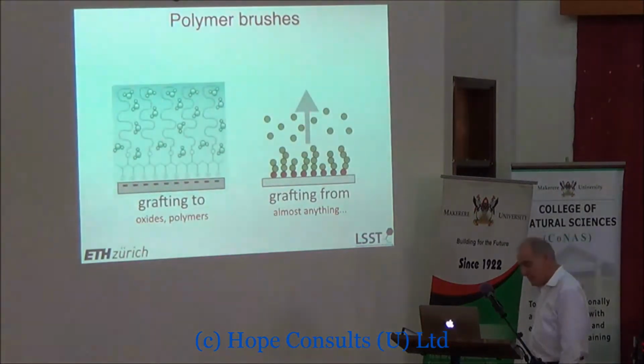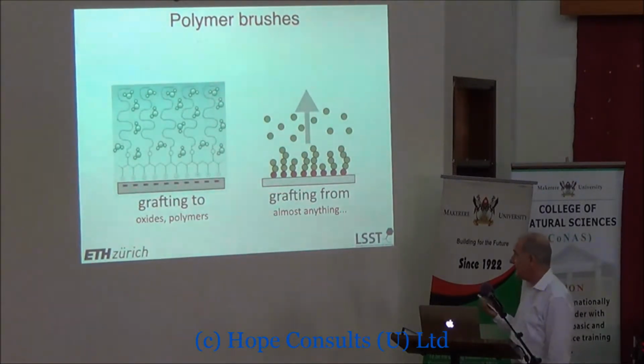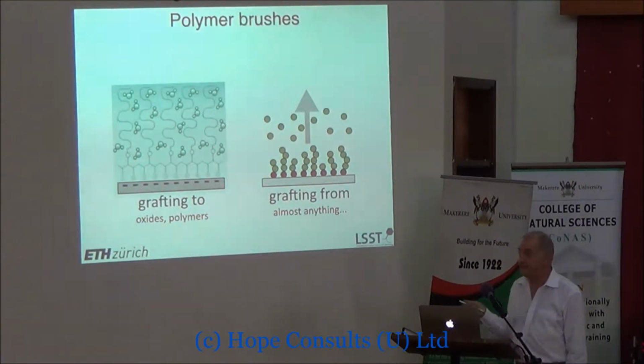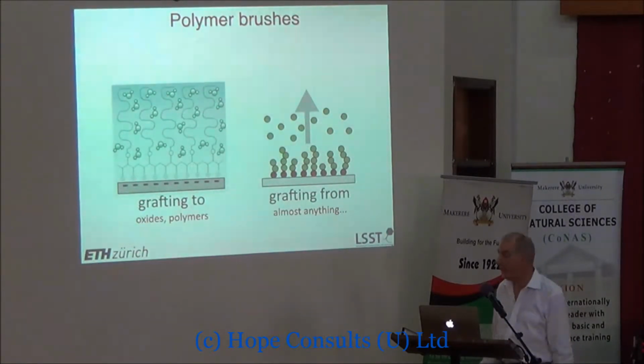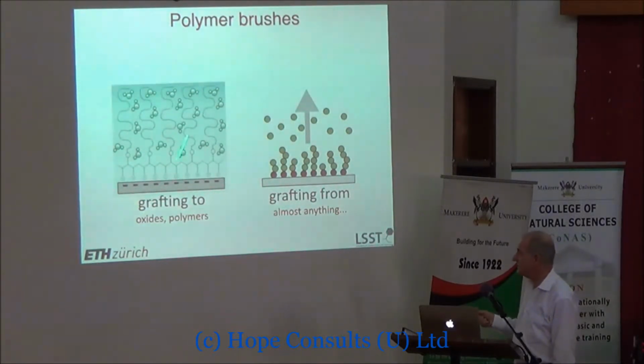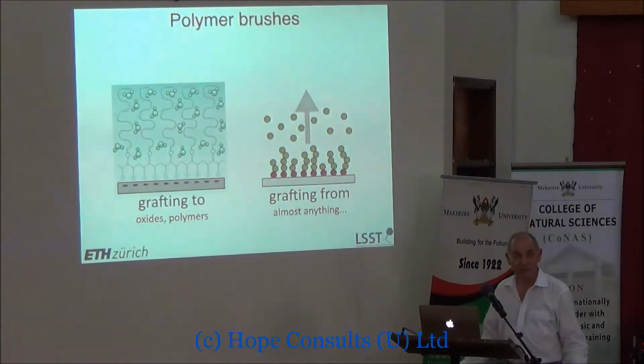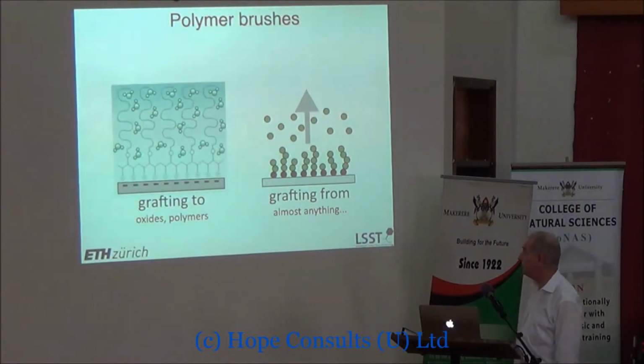Now, there are two ways of making polymer brushes. We can either take a molecule that's ready-made and has some kind of sticky end on it, and stick it onto a surface, and that's an example here. In this case, it's not individual chains, but chains that are attached to a backbone, and then we stick the backbone on the surface. There are a number of reasons for doing that, but basically we've synthesized this to start with, and we put it into solution, rather like we did with the thiols, and then we dip in a surface that's going to interact with it, and then we have a polymer brush just by dipping. So it's very easy to make that kind of polymer brush.